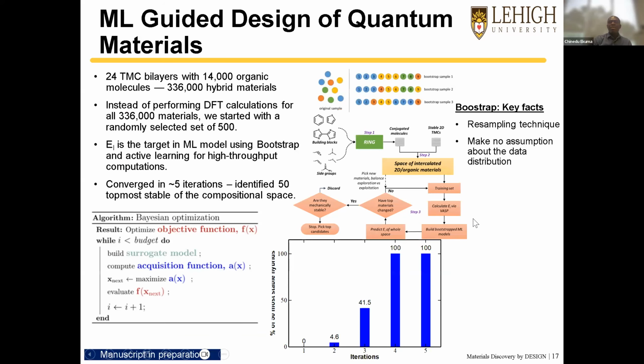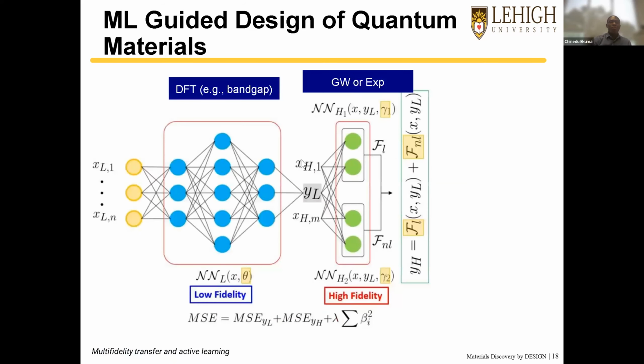Also, within the internal bootstrapping method, we can further engineer the process of exploration and exploitation by using a neural network. One way to do that is, I talked about low fidelity data and high fidelity data. Here we have a bunch of DFT band gaps, and here we have very few GW experimental band gaps. We can use this multi-fidelity transfer and active learning approach to make the low-fidelity data reach the same accuracy level as these by using a multi-fidelity model.